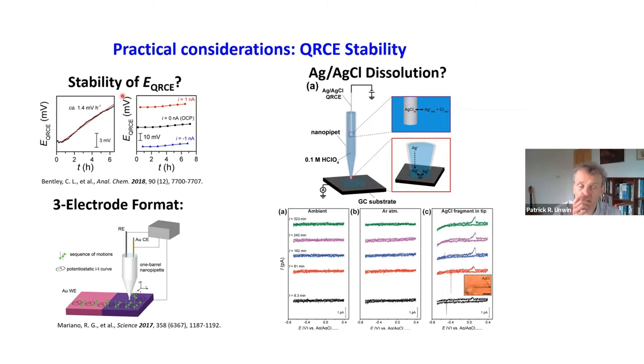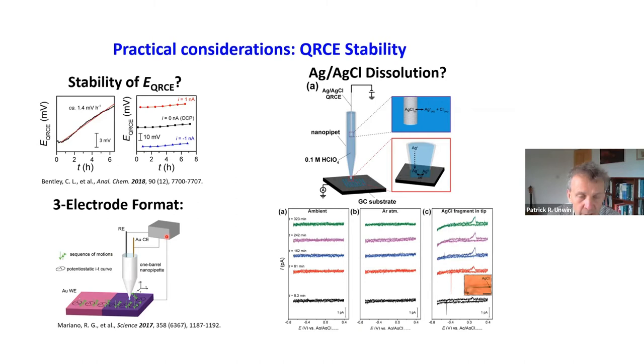These electrodes are also very stable in terms of their potential — a drift of about a millivolt per hour — which is beautiful for doing very nice work on assessing catalysts in this simple two-electrode format. If you're worried about such issues, though they're really not problematic, you can go to a three-electrode format as well. Most recent work on CO2 reduction has used a two-electrode format.